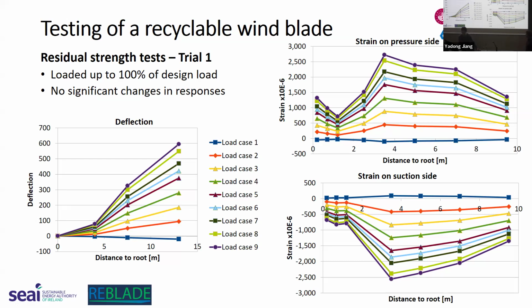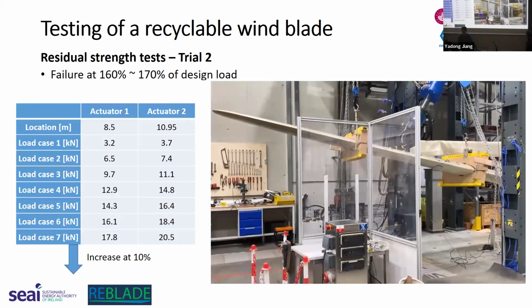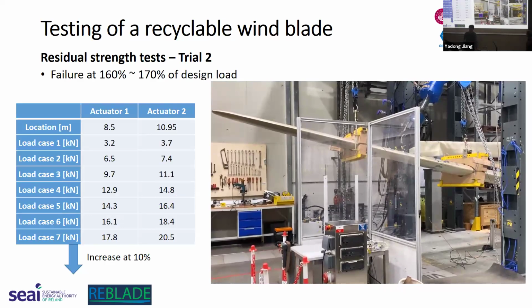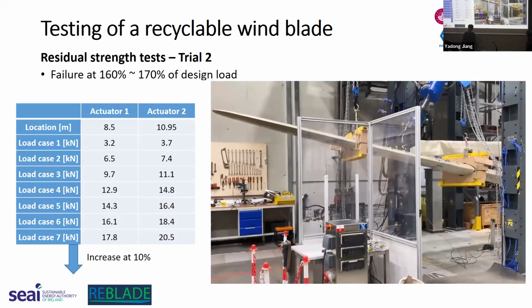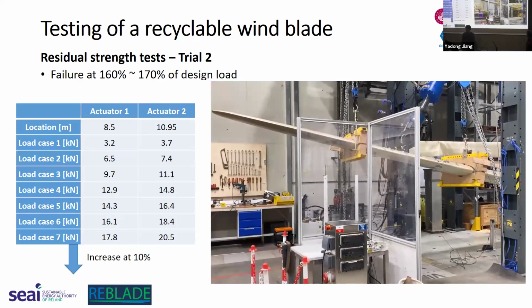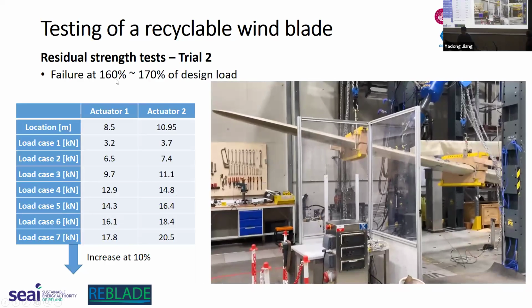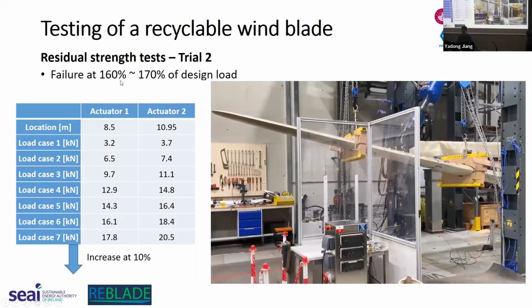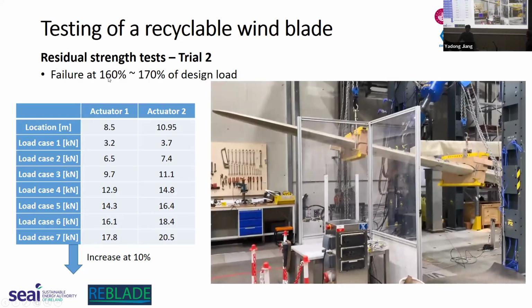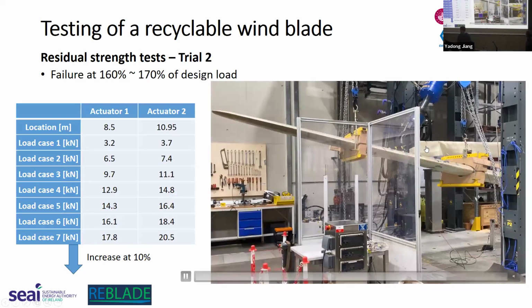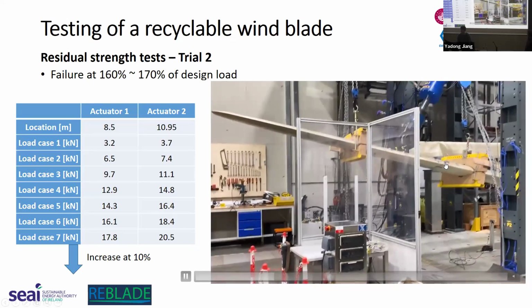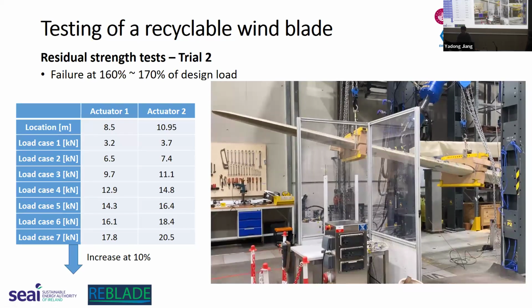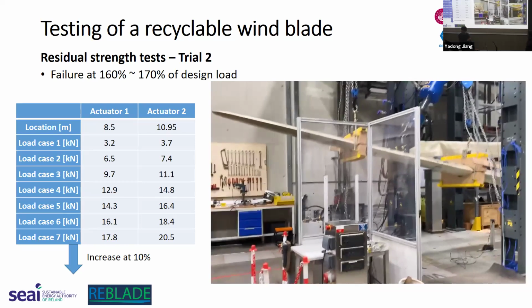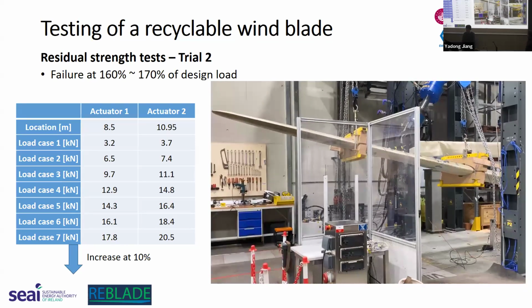And after that, we decided to continue the static test. Here we load up to 100% of design loads and increase in 10% steps. And finally, we broke it at a load which is 60% to 70% higher than the design load. At that point, there is a complete failure at a distance of roughly 3.5 to 4 meters from the root. And here is a video that shows the moment the blade broke, and you can see there is a huge amount of energy released from the composite material.